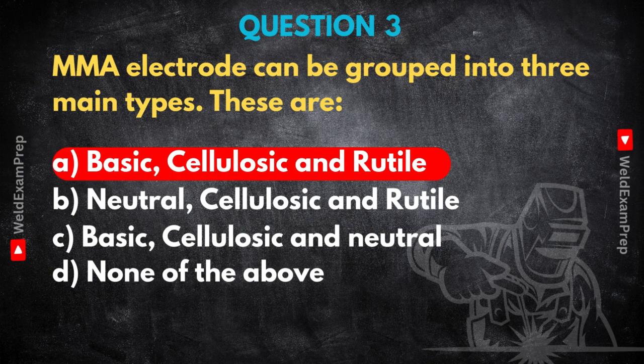Then you've got cellulosic electrodes. People sometimes call these the digging rods. They give a really forceful, deep penetrating arc. Lots of smoke, a bit more spatter usually. Fantastic for getting deep fusion, so they're often used for root passes, especially in pipelines, and for welding downwards quickly. One advantage: they can sometimes handle joints that aren't perfectly clean or fitted up because that strong arc can kind of burn through stuff. An inspector on a pipeline job would expect to see cellulosic for those tough root passes. Speed and deep fusion are key there.